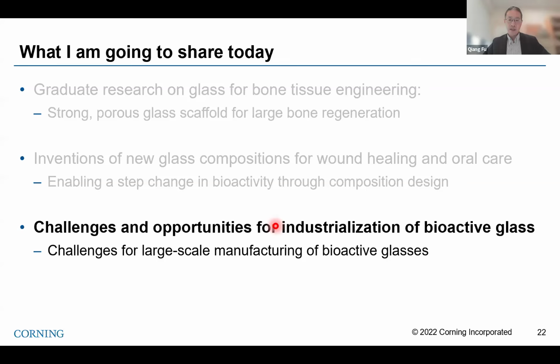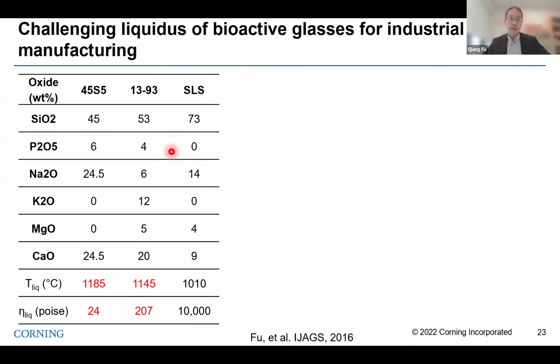I want to show you the challenges and opportunities for mass producing bioglass. If we look at the composition of the traditional 45S5, 13-93 glass compositions versus soda-lime, you will notice soda-lime has much higher silica. I think one key attribute brought by this high silica is its lower liquidus temperature and much higher viscosity. Compared with 45S5, which has a viscosity of around 24 poise, and 13-93, 207 poise, soda-lime definitely has a much higher viscosity, over 10,000 poise. That's one reason why soda-lime is so popular, used in window glass or even for packaging. The glass really has good forming attributes to make into different form factors.